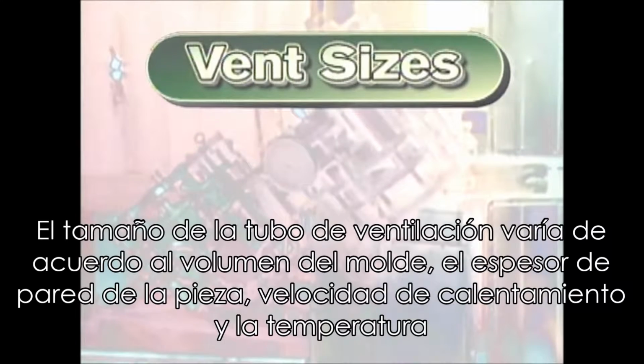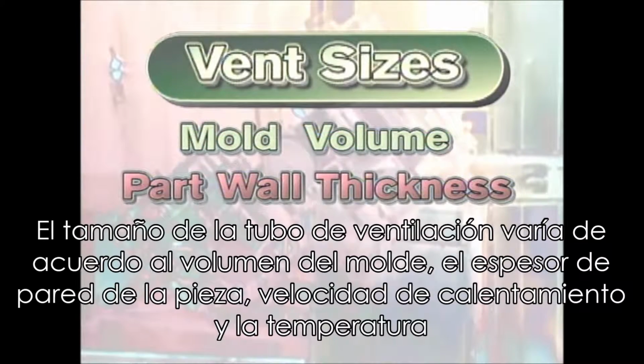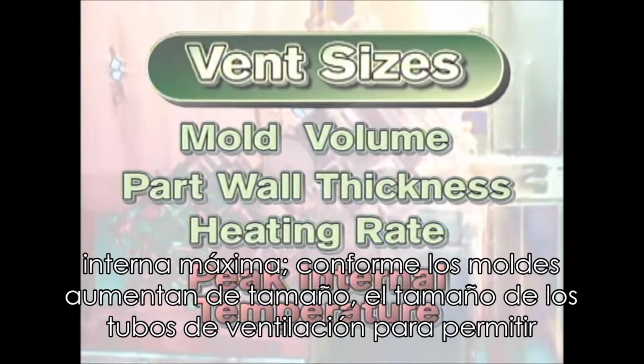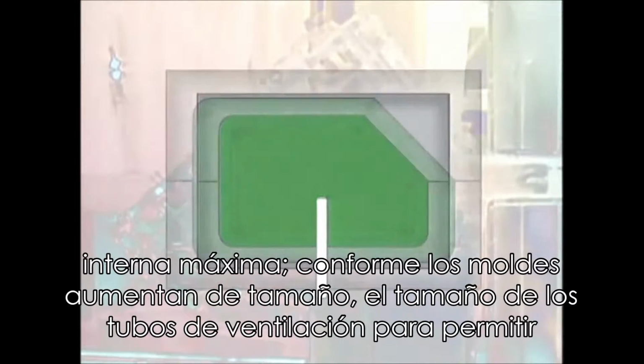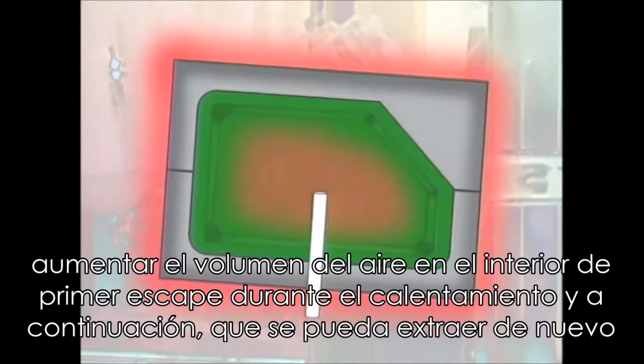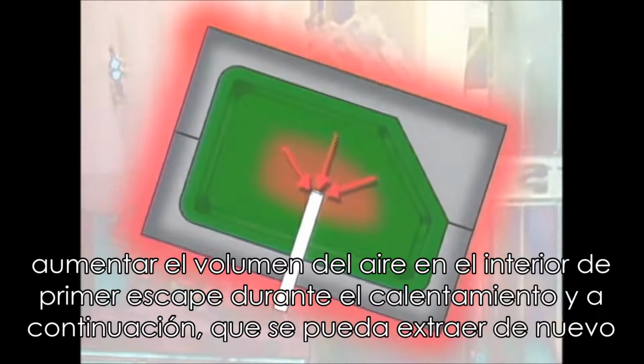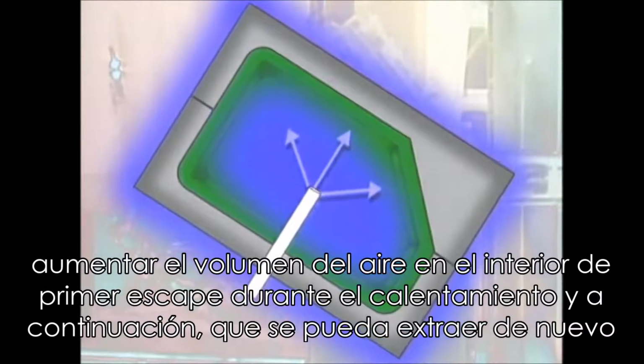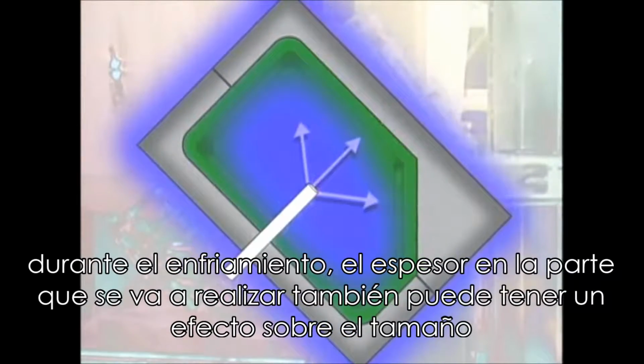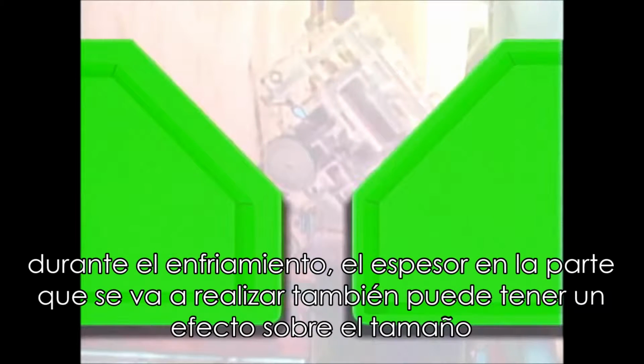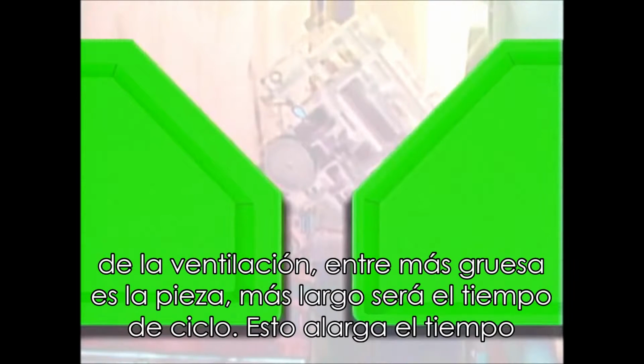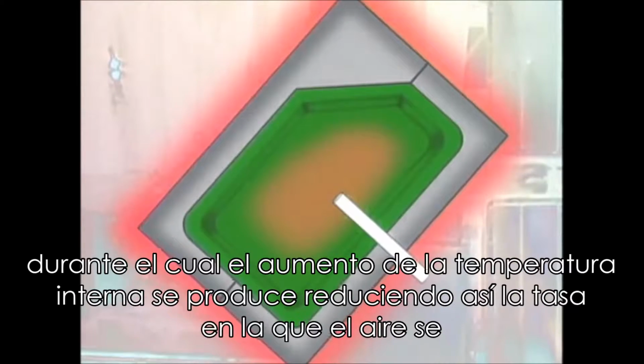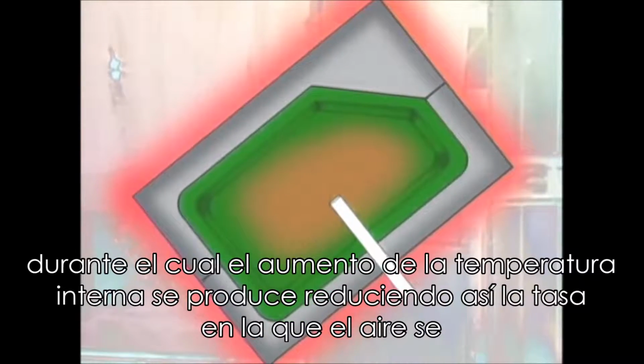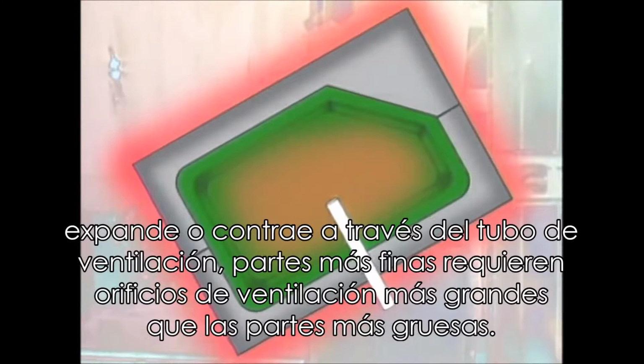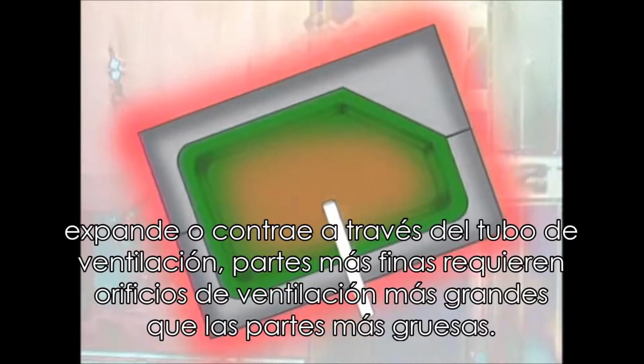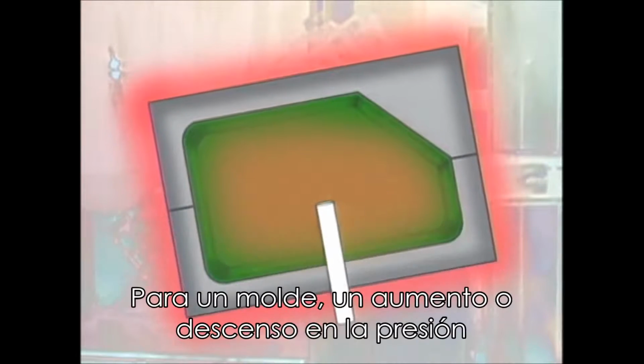Vent sizes vary according to mold volume, part wall thickness, heating rate, and peak internal temperature. As molds increase in size, the size of the vents increase to allow the larger volume of air inside to first escape during heating, and then to be drawn back in during cooling. The thickness of the part to be made can also have an effect on vent size. The thicker the part, the longer the cycle time will be. This lengthens the time over which the internal temperature rise occurs, thus reducing the rate at which air expands or contracts through the vent tube. Thinner parts will require larger vents than thicker parts.